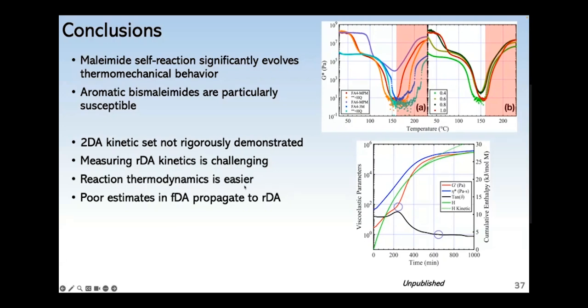I want to be clear with my kinetic analysis. I assumed one forward and one retro Diels-Alder reaction, but the reality is that there's actually two, because of the separate endo and exo adducts having different reaction thermodynamics and kinetics. And if you were to have a complete kinetic description, it would have to reflect both of those adducts. So measuring retro Diels-Alder reaction rates directly is hard. So some studies, like I just showed you, measure the reaction thermodynamics instead, and then calculate the reverse parameters by using the forward parameters as well. The one downfall with this approach is that if you have poor estimates in your forward parameters, those are naturally going to propagate to your reverse kinetic parameters.